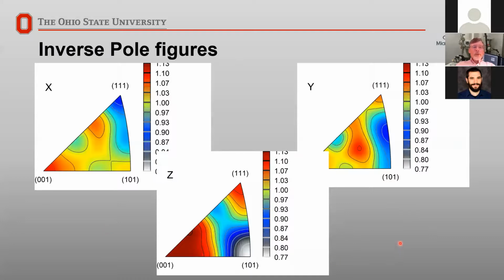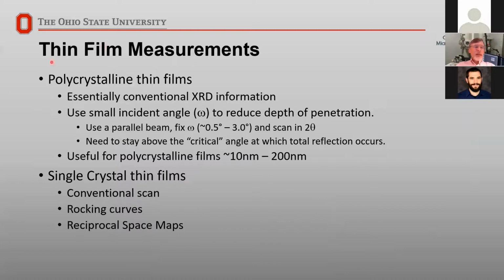So these are all very nicely done in the bulk, but we can also start looking at thin films in our samples. Now we can have thin films that are polycrystalline or thin films that are single crystal. So polycrystalline films would be something like rust or corrosion on a surface. And we can get essentially the same information we get from conventional X-ray diffraction, but we want to keep our scattering right within this very thin layer on the surface. And we can do that by using a parallel beam and then just scanning our detector. It keeps the scattering within those top few nanometers of the sample. So very useful for these films that are sort of in the tens to a few hundred nanometer thicknesses.